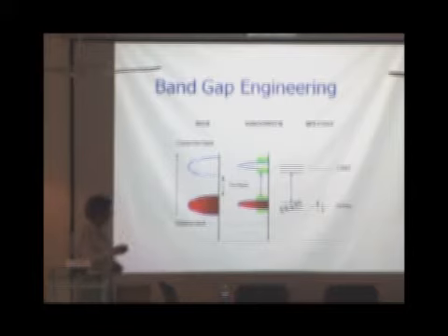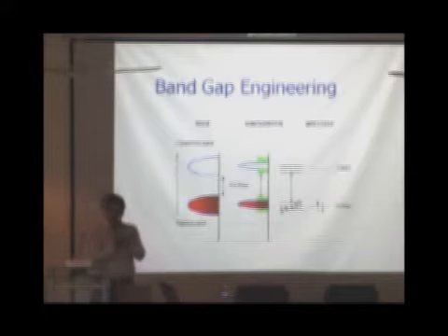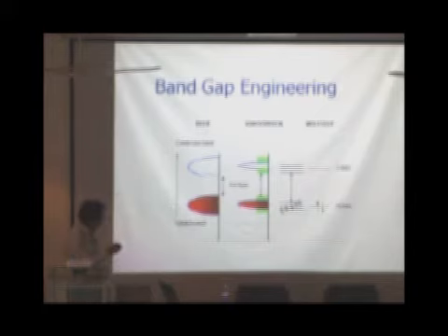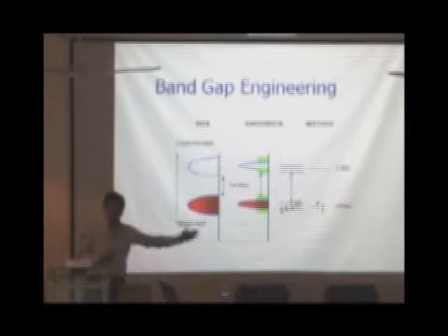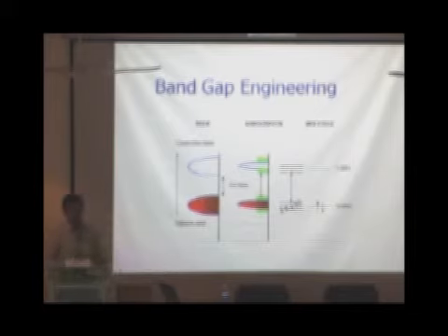So you decrease the size of the nanocrystal, you increase the energy level separation, and that energy level separation can be correlated with the band gap. As you increase the band gap, you increase the energy required to make this transition across the band gap, and you can imagine if it's a smaller size, more energy is required. That means the color of these nanoparticles, which is nothing but the transition from the conduction band to the valence band, is going to be in the blue end of the spectrum, and if you have large particles, then you're going to get red colored fluorescence.